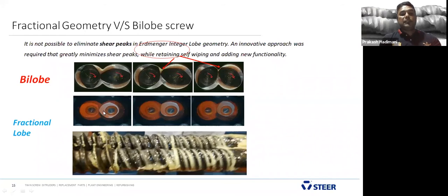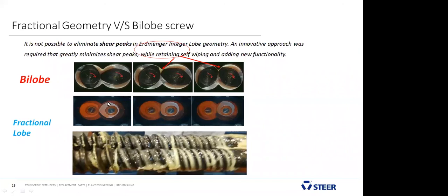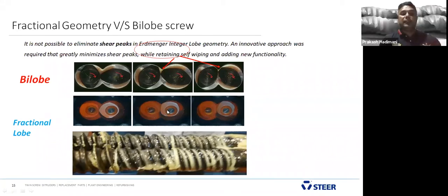In terms of fractional mixing elements, if you see, this is a 4-lobe mixing element, and you have a pool of melt, completely filled with melt here. Even in the last one, when it starts rotating, you have a big gap, every rotation. That is why, because of the 4-lobe construction, you have a uniform shear rate throughout the system. There's no degradation. The photo below shows the input raw material is white in color, and finally at the metering section, the complete blend is white in color.